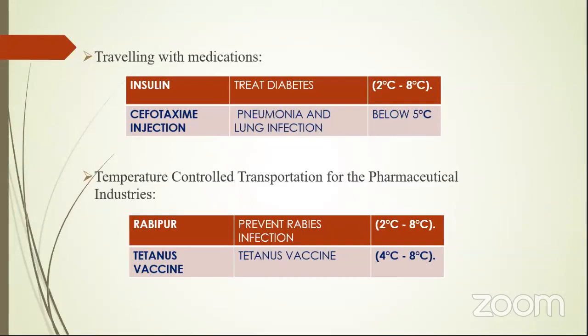And this is a small example of why we need phase change materials and what the reasons are, right? If you take medications while traveling, we have to keep the temperature at 2 degrees Celsius to 8 degrees Celsius. And the cefotaxime injection, we have to keep below 5 degrees Celsius. So we have to keep some constant temperature. And while traveling, how can we keep it? For that case, we depend on PCM materials. So these PCM materials help a lot to maintain the temperature of these medications, because almost